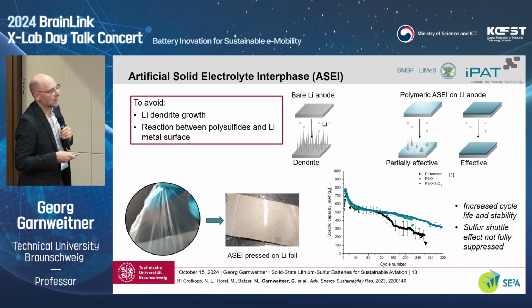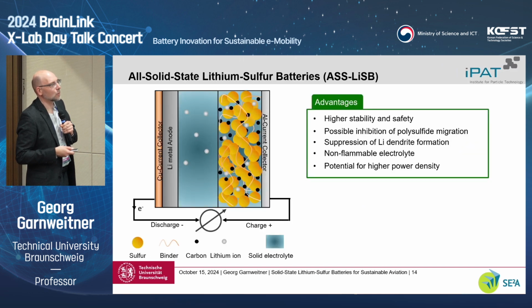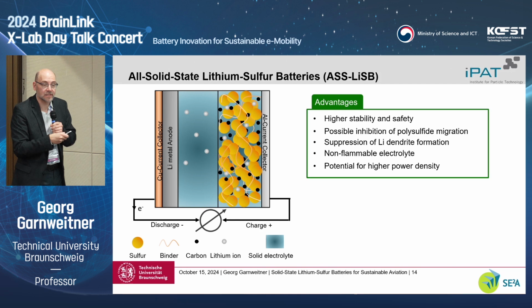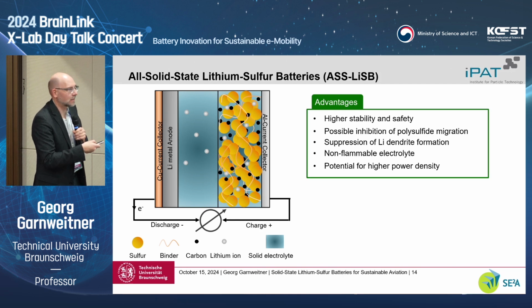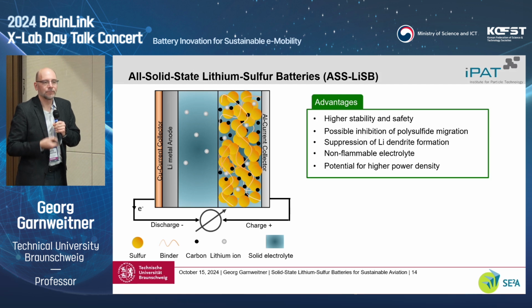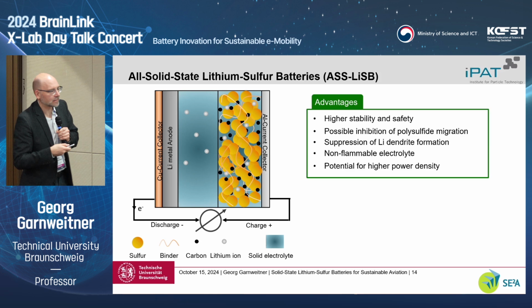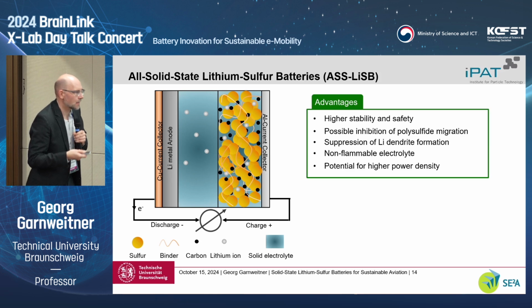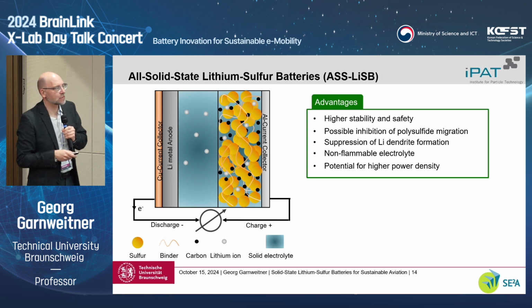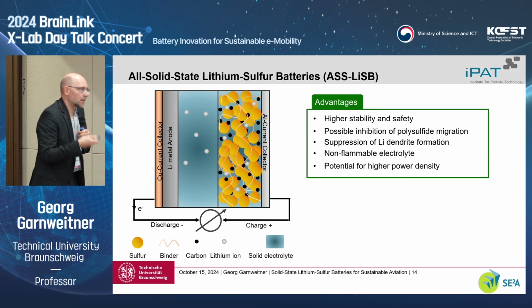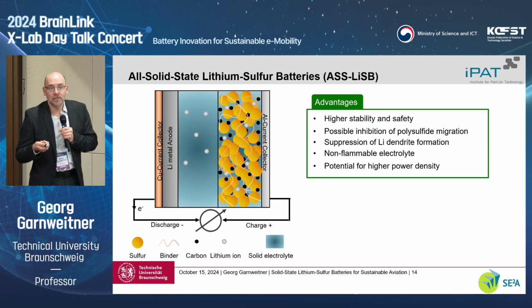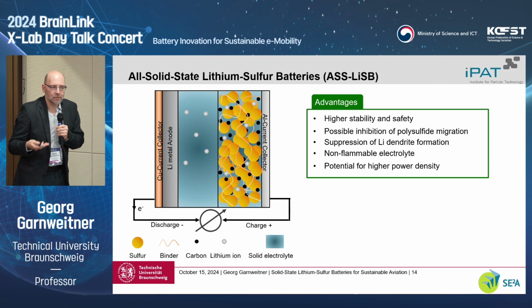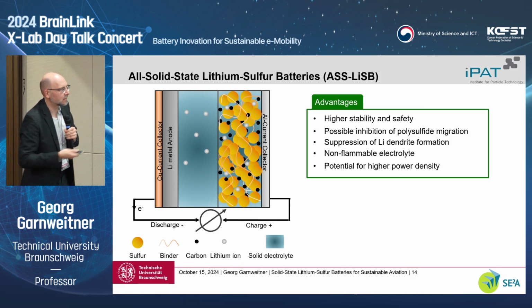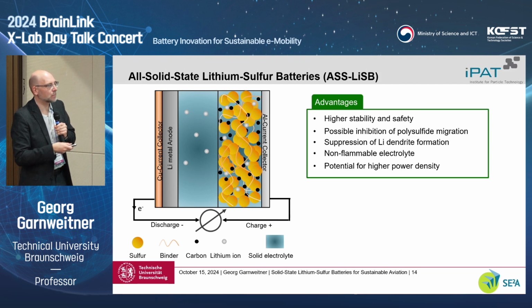shuttle effect, which is why we decided to go one step further to a true all-solid-state lithium-sulfur battery, where we replaced the liquid electrolyte by a solid one, and we decided to again have a polymer as the electrolyte compound in this system. Ideally, you then have a number of advantages that you can combine. Of course, also for aviation, this is highly desirable because of safety aspects. The electrolyte cannot leak, it's non-flammable.